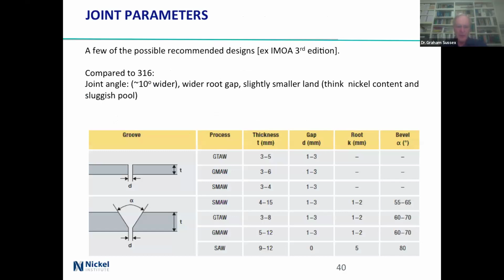Okay, what about joint parameters? How do you put it together? This is again lifted straight out of the IMOA Nickel Institute publication, looking at, compared to 316, a wider root gap, perhaps 10 degrees wider, and a slightly smaller land at the bottom to retain the stuff, just to think about the nickel content, and it's sluggish, so you don't want to have it not going through there. You actually want to get it through, otherwise you wind up with lack of penetration. And this is just a series of recommendations.